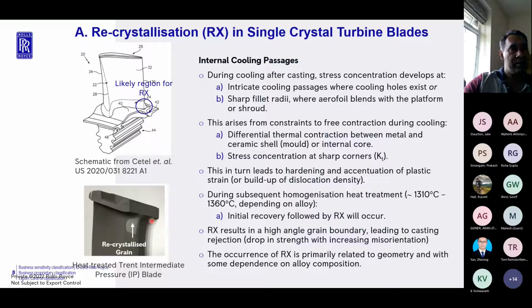So typically, you can see this is a portion of a heat-treated IP turbine blade. Unlike in the case of an HP blade, the IP blade has a longer aerofoil, and you can see in the region around this sharp fillet, you've got this recrystallized grain, which is maybe of the order of a couple of millimeters. So this blade then immediately gets scrapped. And the cost of this blade at the time it reaches heat treatment is of the order of at least about 300 to 400 pounds. So you can imagine the amount of non-conformance you could get through heat treatment if you have a component with a high degree of plastic strain.